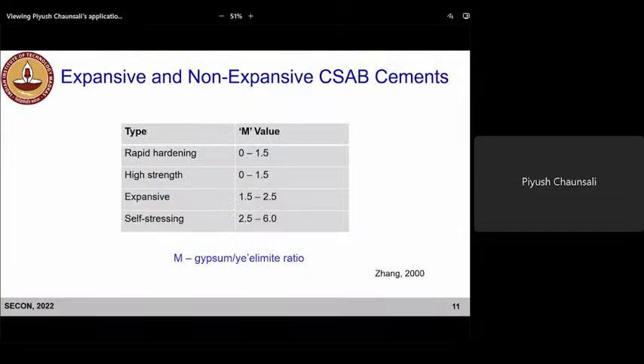Now we can have both expansive and non-expansive cements. In some cases, we don't want expansion. How do we then tailor or manipulate this property? So here you see the M value is nothing but a ratio between gypsum and yeelimite. Yeelimite again is C4A3S, the calcium sulfoaluminate phase. So this ratio will affect its hardening behavior and also expansion. So in this case, if the M value is greater than 1.5, the system expands. Okay, and if the M value is below 1.5, then it's not an expansive system, but you are able to get rapid hardening, high strength. So as a user, this is one way to manipulate its expansion and accordingly the hardening behavior.